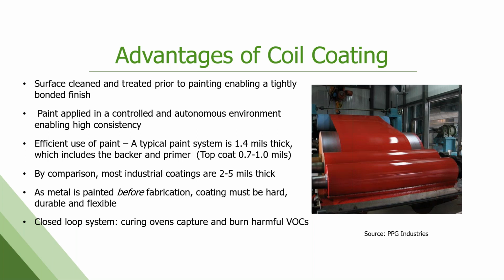Very efficient use of paint. So we're putting this on about 1.4 mils total of paint, and that includes the primer, the top coat, and the backer. By comparison, most industrial coatings are like 2 to 5 mils in thickness. That's 2 to 3 times thicker than the paint we're putting on this material.